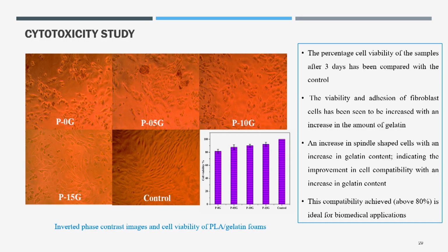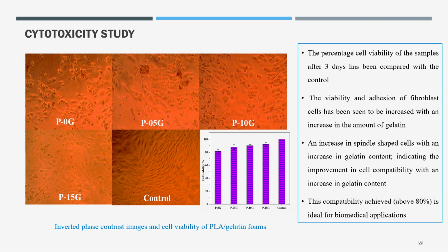And then we conducted the examination that Noel presented previously. This is called cytotoxicity. You spread some cells on your matrix, and after some time, if the cells are dying, do not use it further, because that is evidence of toxicity. Mouse L929 cells are spread on your system, and we wait to see what happens. We can see whether the cells die or not. If the cells die, you will not see any image, but you can see the control sample. You have to compare with the control sample there, no? And for your P-10G, you can see small cells. Even after many days of incubation, cells are alive.